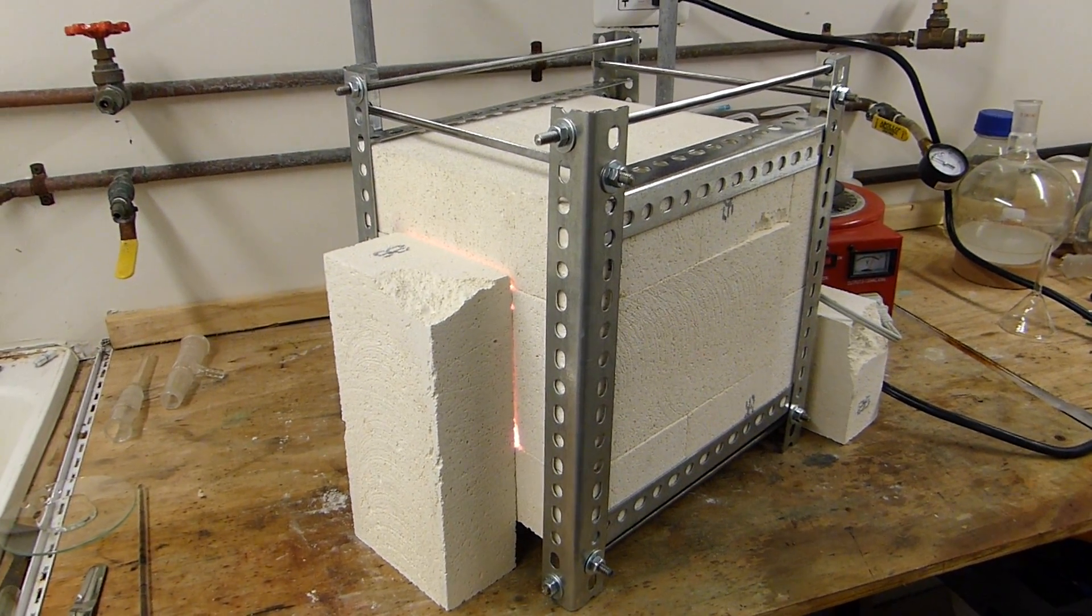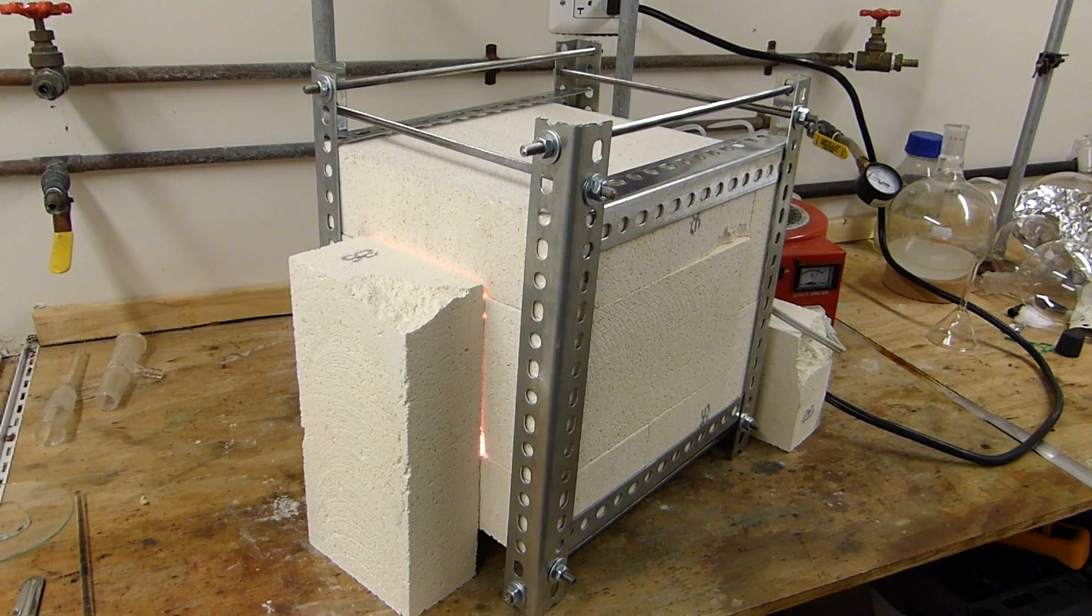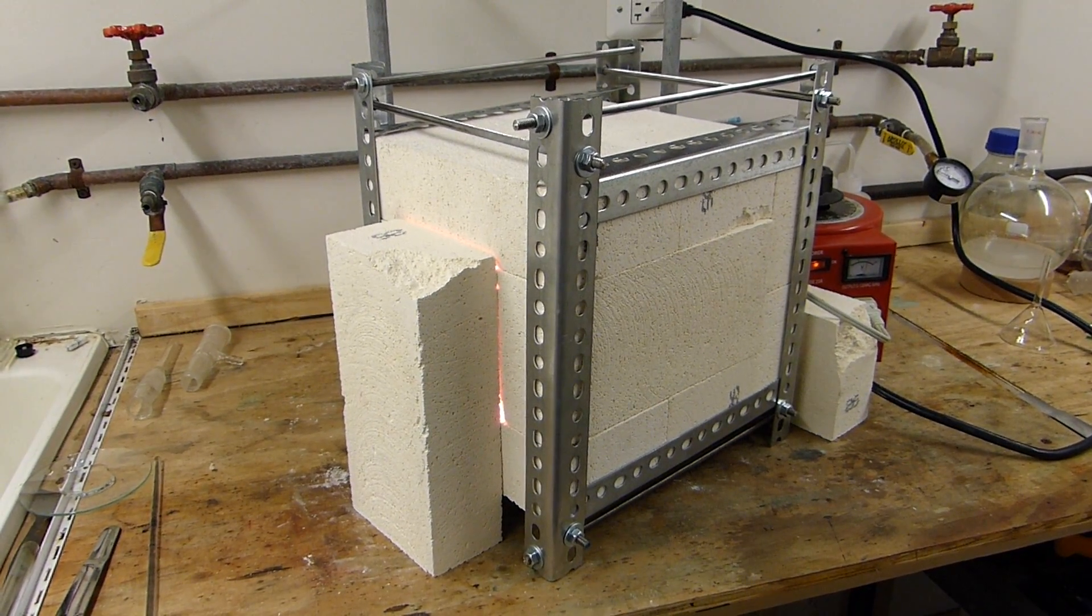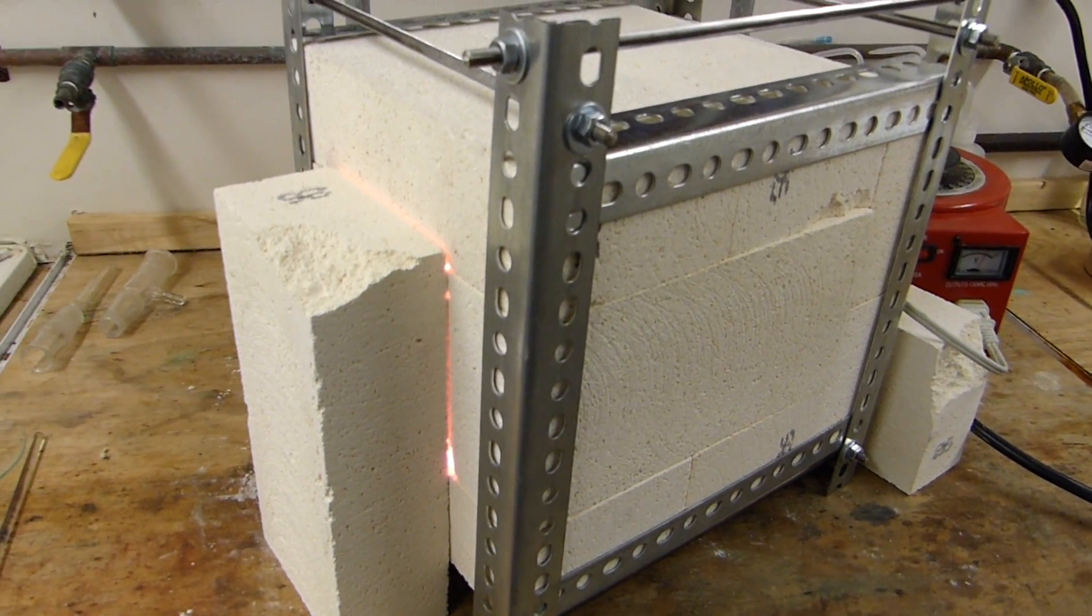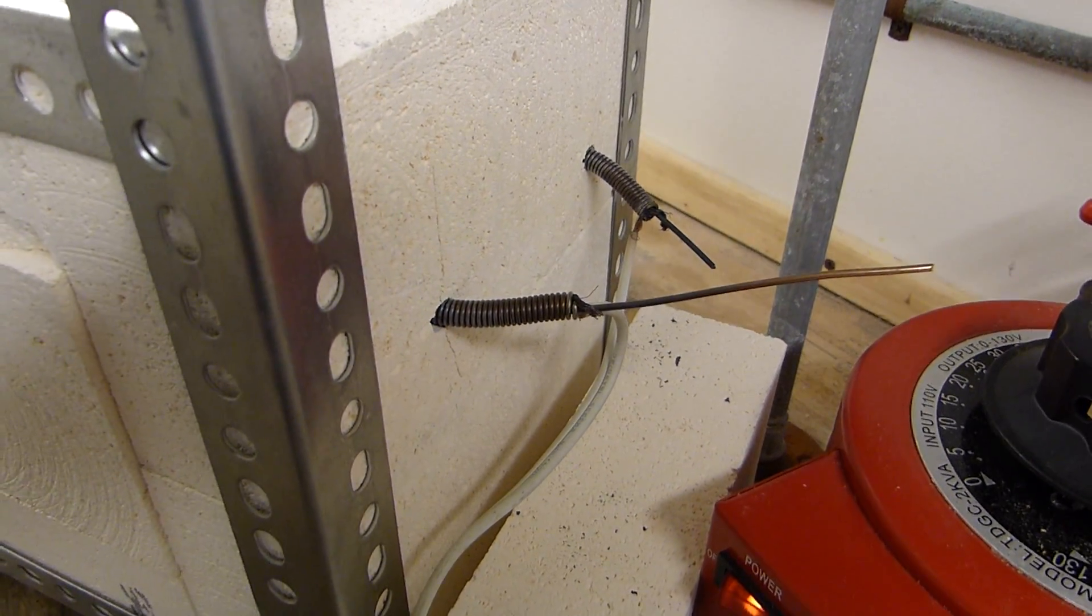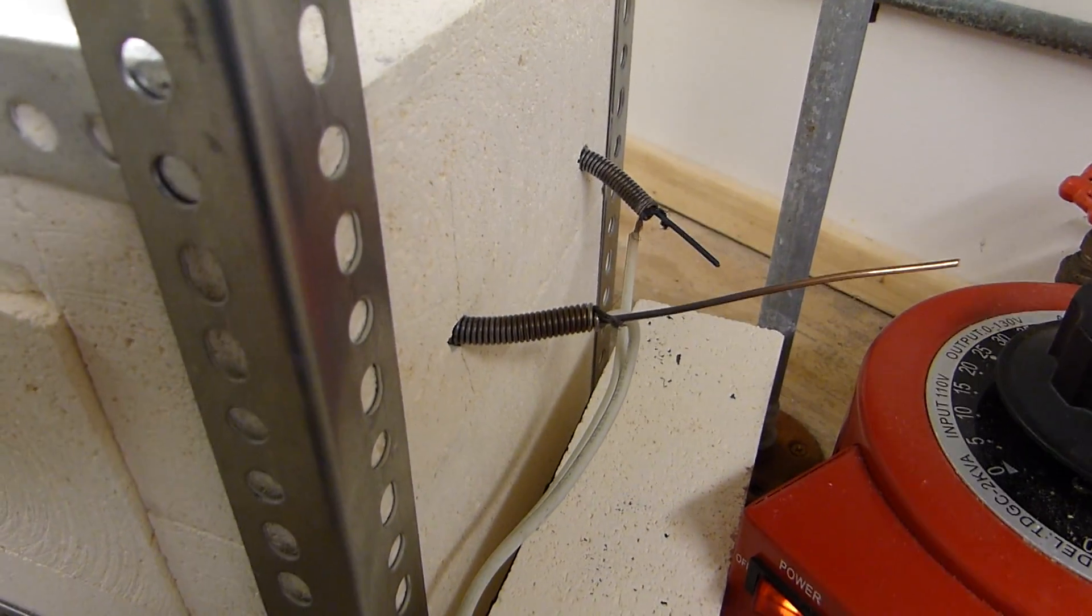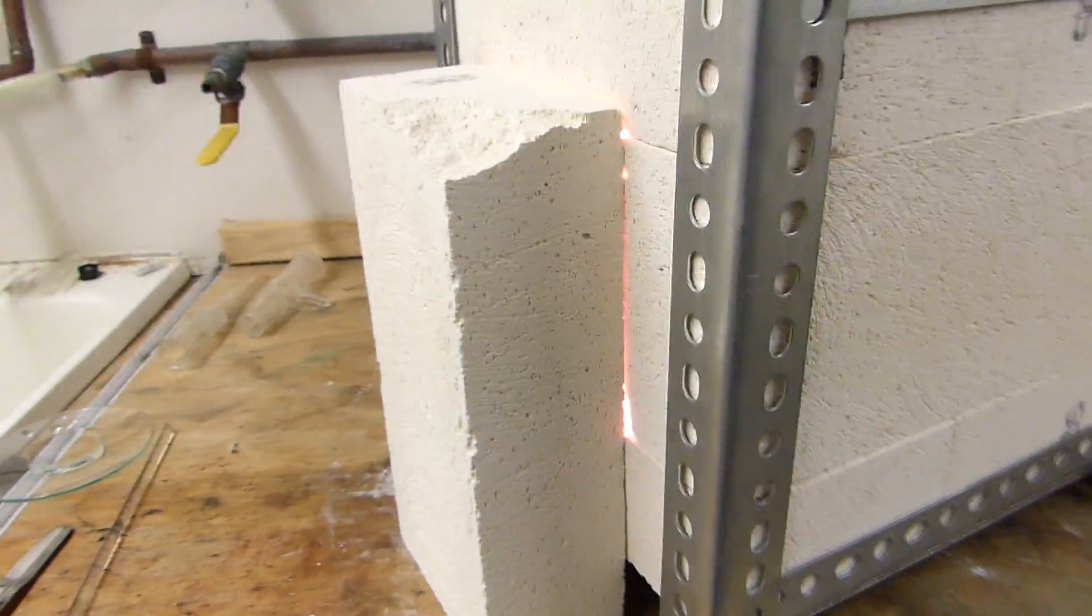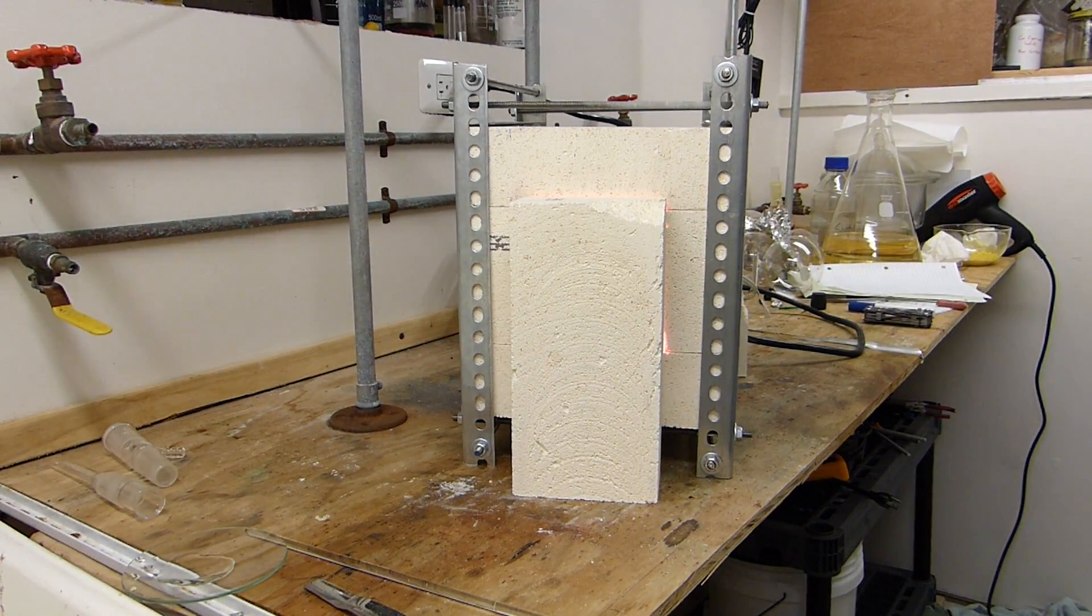All right, it's been running for about a half an hour now. I don't know if the copper's melted, but copper melts at 1,085 Celsius. Aluminum melts at like 660 or something like that. The maximum service temperature of this furnace I had intended to be 1,200 Celsius, which is a full 300 degrees below the melting point of this particular alloy of resistance wire that I'm using. I did insert these little pieces of copper here into these electrodes, and that seems to be working really well. What that does is basically shorts out all of the coils that are inside that fire brick. So it prevents them from carrying a whole lot of electricity, and thus prevents them from overheating. It's probably 900 C or something maybe. We've got to be getting close. I'm going to open up and check on it.